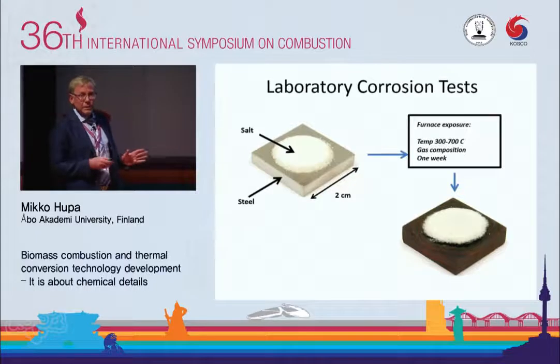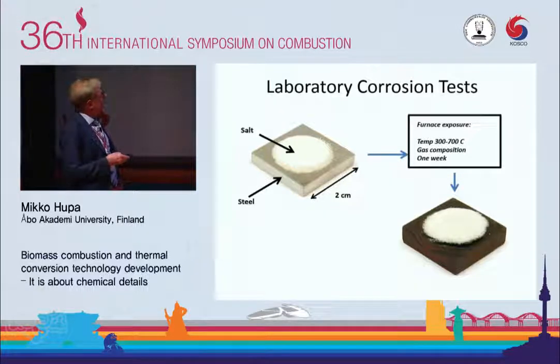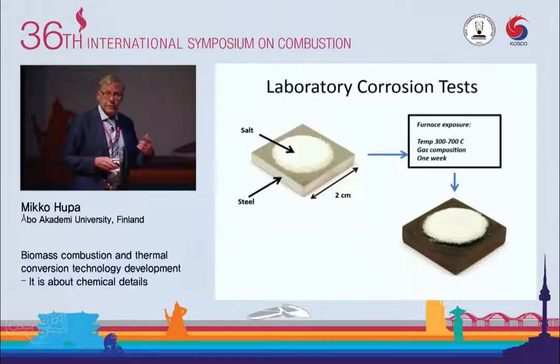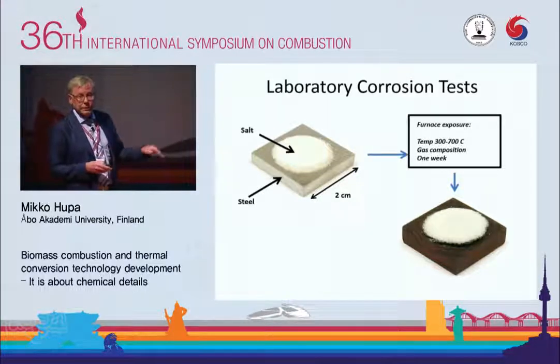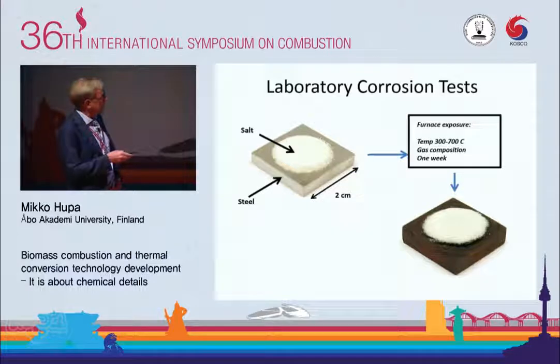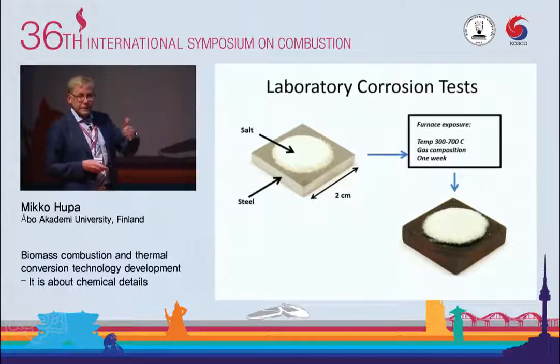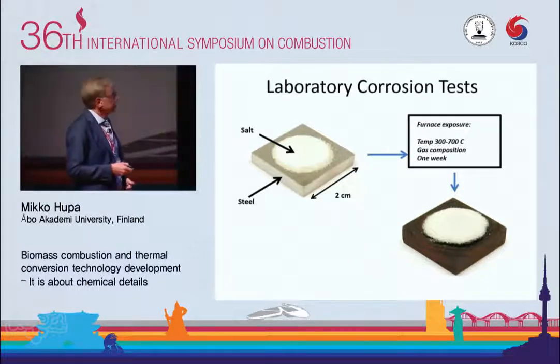In our laboratories, when we do corrosion, we do it quite simple. We have a sample plate of different steels. We put some salt on top of them, treat them in a furnace-controlled atmosphere. 1 week has shown to be a long enough time to get a good signal. And then we cut the piece and do microscopy on that.